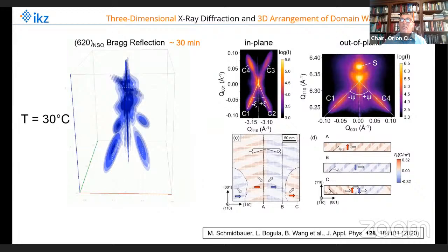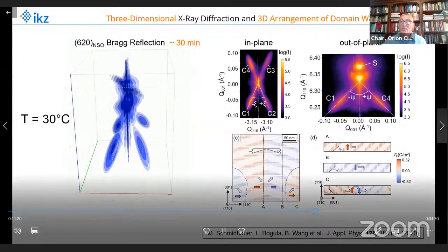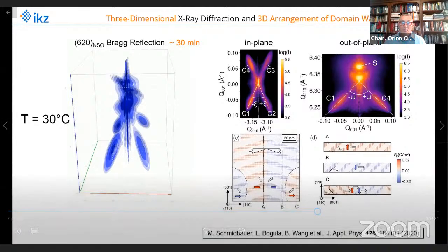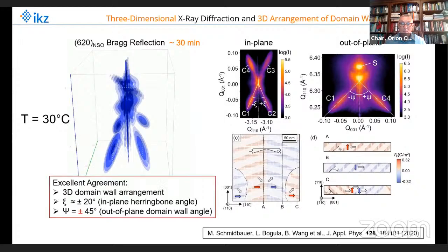In order to make it more clear, I have made in-plane and out-of-plane sections at the right side of the transparency, and you can directly compare this to three-dimensional phase field simulations. And they again perfectly fit. So for example, the in-plane herringbone angle Xi is reproduced. It gives us 20 degrees, also in the phase field simulations. But more importantly, also out of plane, you see domain wall angles of plus minus 45 degrees in the experiment. And this is also exactly reproduced in the phase field simulation. So again, a very, very nice agreement.